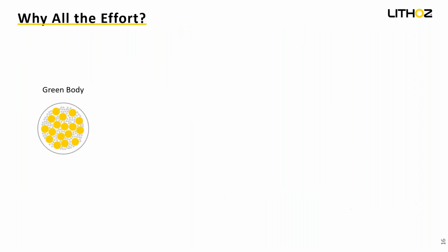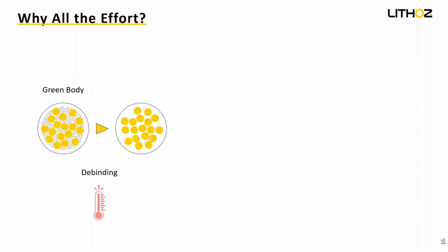In the green state, the part is made of two components. The yellow dots represent the ceramic particles, and the gray areas represent the organic binder that holds everything together. At this stage, the part is still fragile and not yet a ceramic. During thermal post-processing, we first remove the binder, and then we sinter the ceramic particles together.